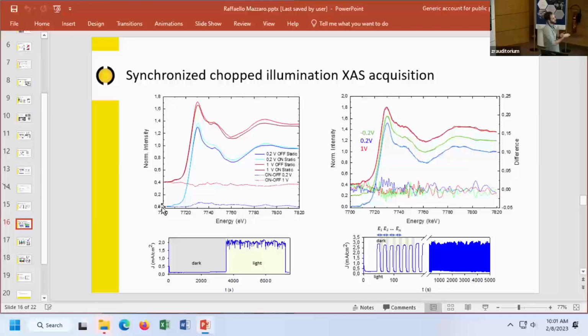And as you can see, in this case, we have good and bad news. The good news is that these spectra are exactly the same as each other. So on and off, you cannot even recognize the on and off spectra. And that means that the measurement is very stable. So we don't have any problem in the stability of the measurement. But on the other hand, we have some issues related to the fact that we don't see any effect of the light. So at least in this kind of experimental setup, we don't see anything, except for a very small change in the 0.2 volt spectrum. You see here, this bump here.